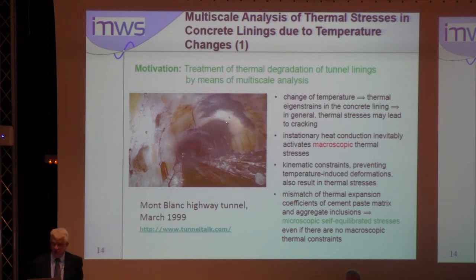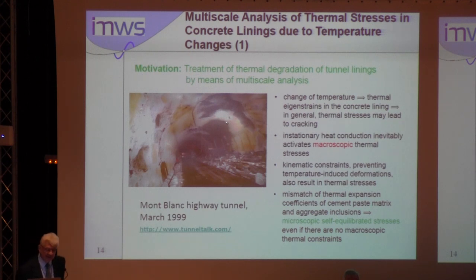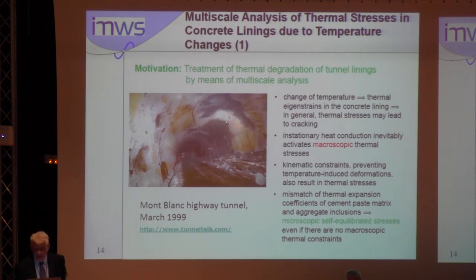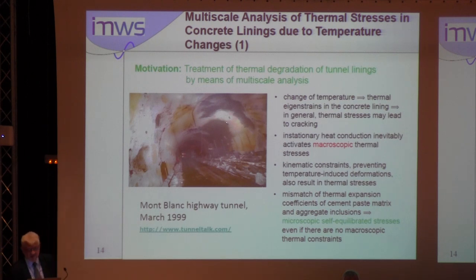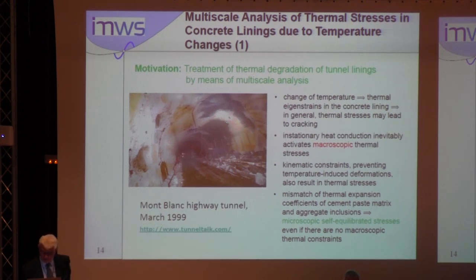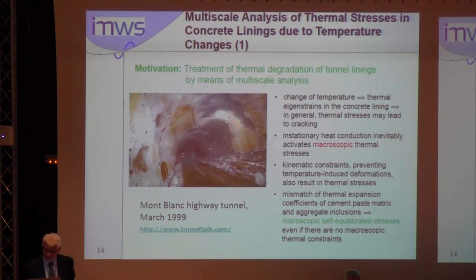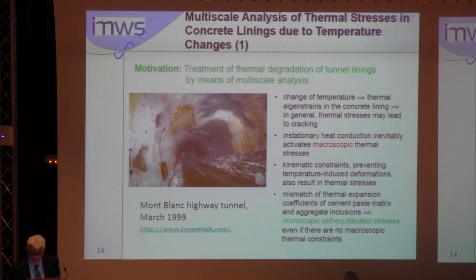The motivation for the second part is treatment of thermal degradation of tunnel linings by means of multiscale analysis. The figure shows the Mont Blanc highway tunnel after the accident in March 1999. A change of temperature results in thermal eigenstrains in the concrete lining. Thermal stresses may occur and lead to cracking for several reasons: instationary heat conduction inevitably activating macroscopic thermal stresses, kinematic constraints preventing temperature-induced deformations, and the mismatch of thermal expansion coefficients of the cement-based matrix and the aggregate inclusions, resulting in microscopic self-equilibrated stresses even without macroscopic thermal constraints.